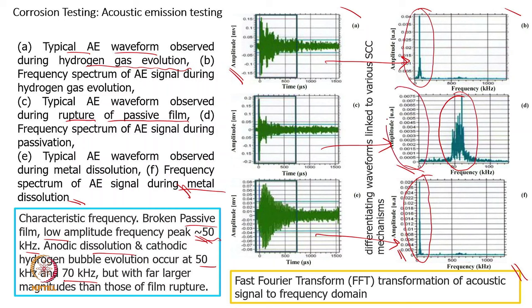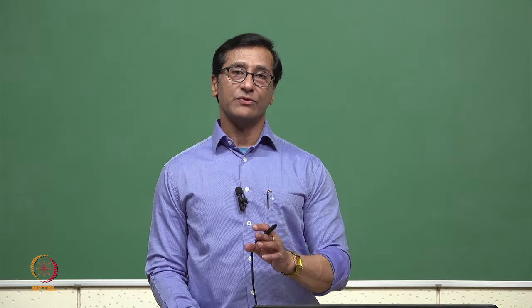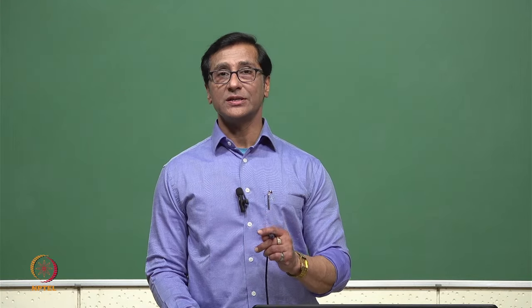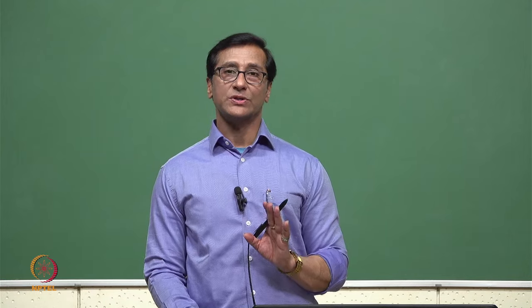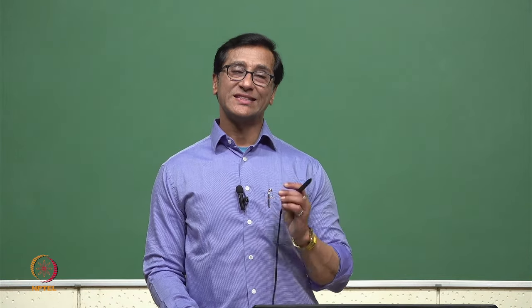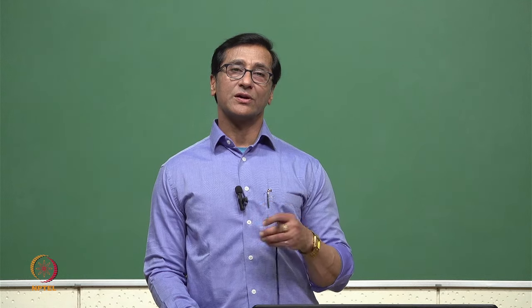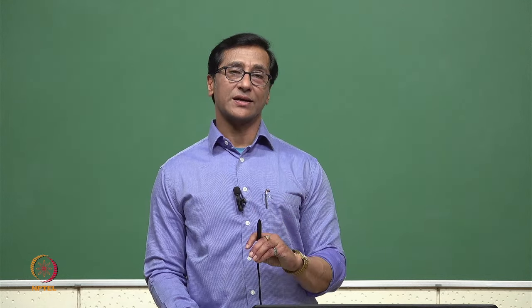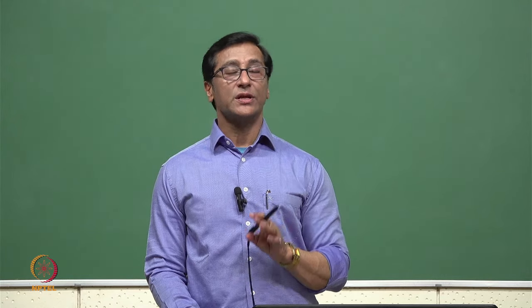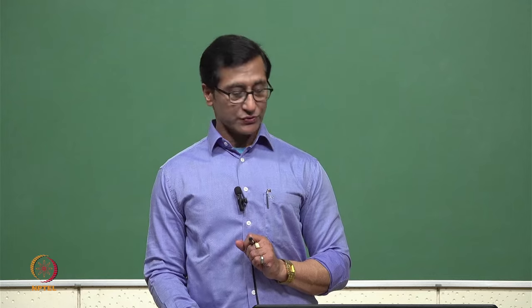In the B case, particularly, it is much lower, and in C and D we are getting passive film rupture at a lower magnitude, while in this case we are getting a much higher magnitude. So these are comparable results, and by analyzing the signal appropriately we can find out what kind of fault is there. One is the detection of the crack, which the acoustic emission signal can do. But going further into detail, even the inception or mechanism which is causing a crack to initiate and propagate can also be captured. That's why this will be very useful to us.